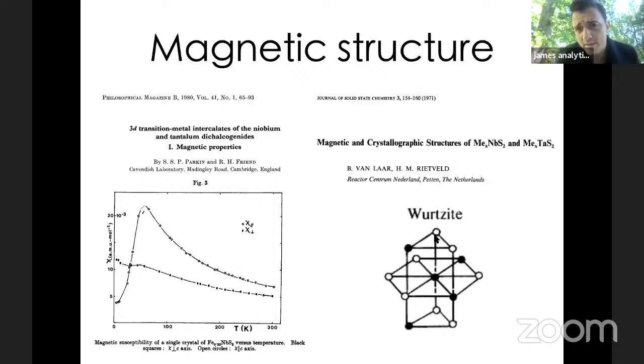Now, in terms of the magnetic structure, there was also a determination around the same time of what the magnetic structure would look like, and you can imagine the spins are actually pointing north and south on this diagram. But it turns out that this magnetic structure is a bit controversial. A couple of decades later, another magnetic structure was determined that saw, instead of this zigzag type structure, a stripe type structure. You don't have to remember that until the very end, but it's important to know that the magnetic structure actually wasn't very well understood, I think until myself and our collaborators explored the system in detail.